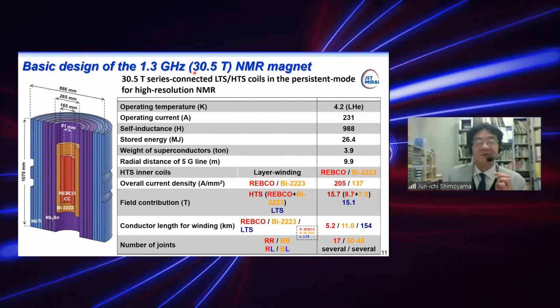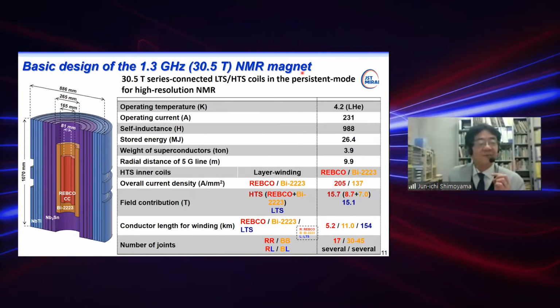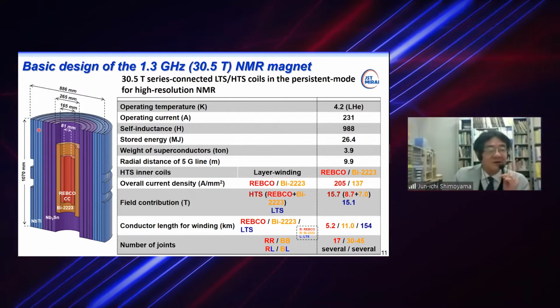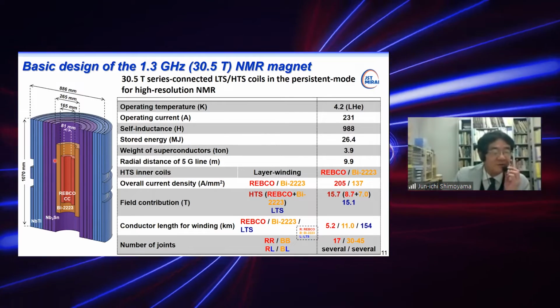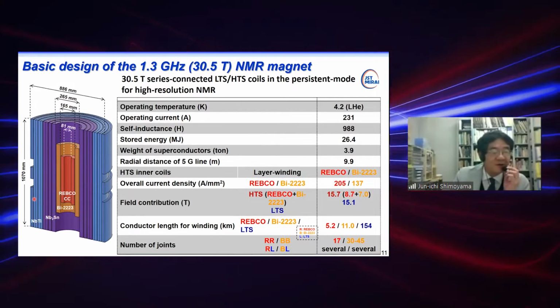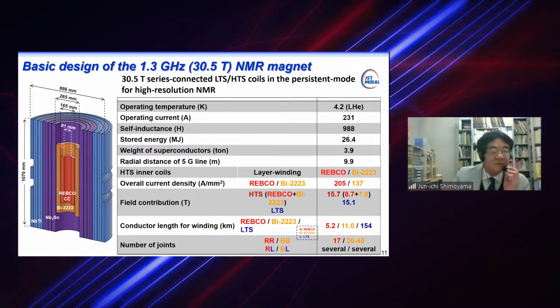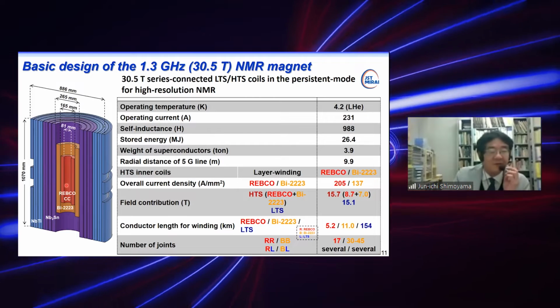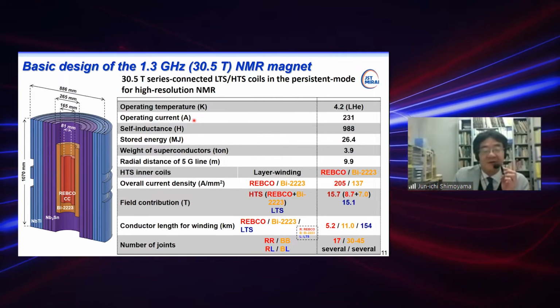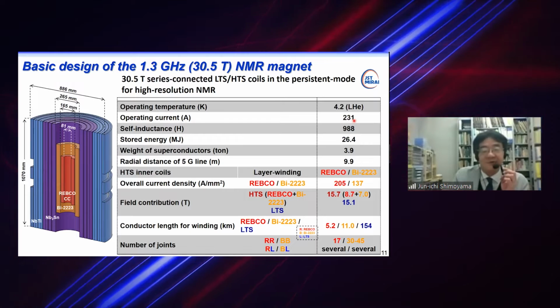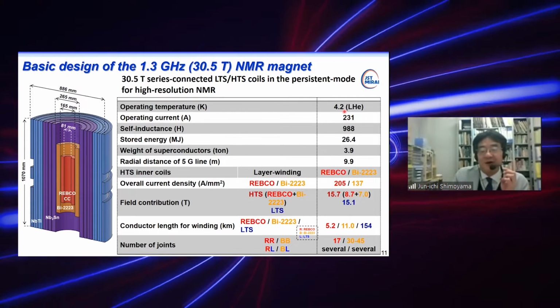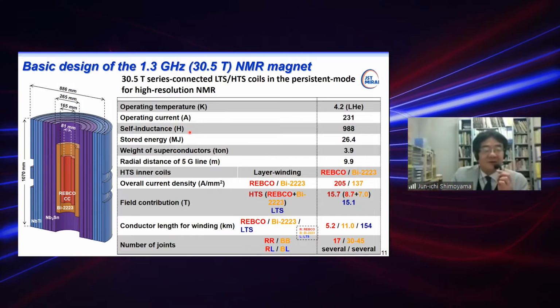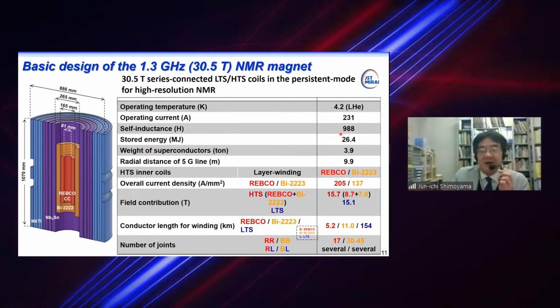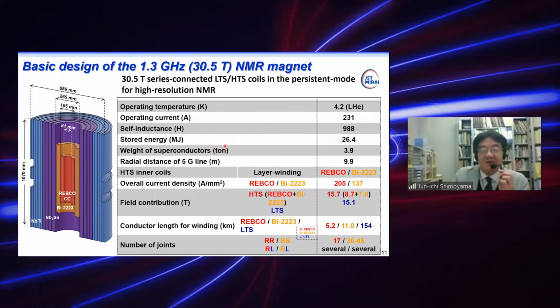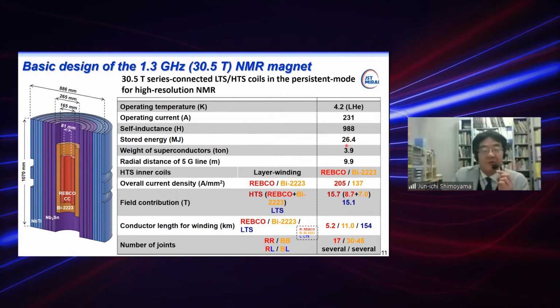This is the basic design of the 1.3 gigahertz, that means 30.5 Tesla NMR magnet. This is a very big one, as you see here. You can see 4 superconductors are used in this magnet: niobium-titanium, niobium-tin, Bi-2223, and REBCO coated conductors. The operating current is designed to be 231 amps, and the operating temperature is 4.2 Kelvin. Self-inductance of this big magnet is very large, 988 Henry, and stored energy is very large, 26.4 megajoules.